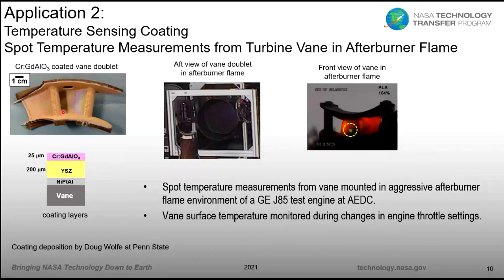And you can see what we do. We put our chrome gadolinium aluminate coating on the top, 25 microns thick. We have that deposited at Penn State by Doug Wolf using electron beam physical vapor deposition. And that coating gives the coloration you see on the vane surfaces here. It's on top of an yttria stabilized zirconia thermal barrier coating, which is typically on the component to begin with. That's for thermal protection. And so that's white. So this would look white if we didn't have this phosphor coating on top.